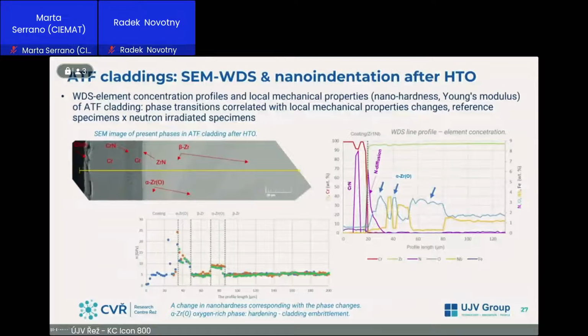What we also evaluate on ATF claddings is after high temperature oxidation, where we developed the method of chemical profiles and the nanoindentation profiles which we compared. And there is the chemical change correlated with local mechanical properties. So from this data, we can evaluate the phase changes in reference as well as irradiated materials. So here are the profiles of the chemical and local mechanical changes.